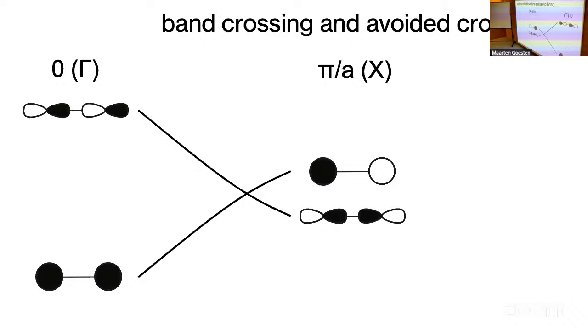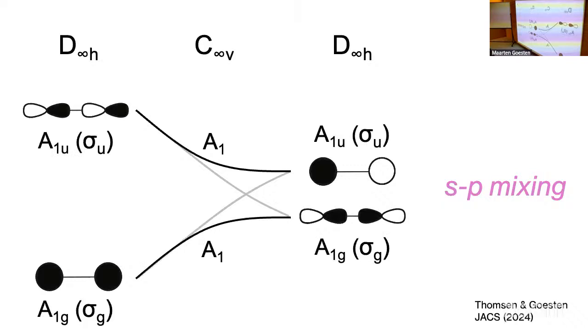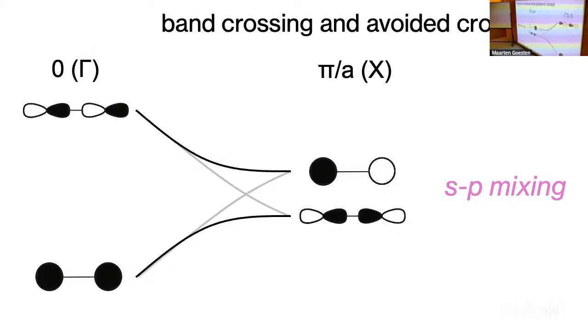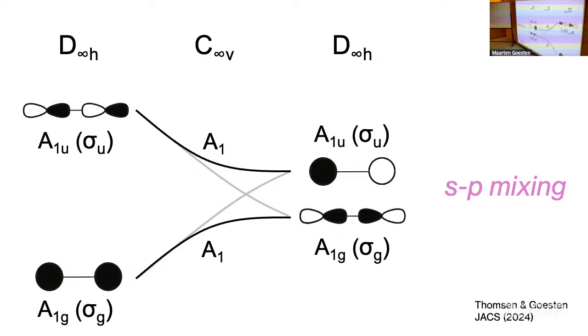distinguished by parity. So if you lose inversion operation, what actually happens is that within this point group, these two orbitals obtain the same irreducible representation. So instead of crossing, what you would expect to happen here, this s band starts interacting with the top band, and increasingly much p orbital character is transferred into the bottom band. Increasingly much s orbital character is transferred into the top band. What happens is that this band is fully p character on the left and becomes fully s character on the right. So the reverse is true here. This is fully s on the left, becomes fully p on the right.